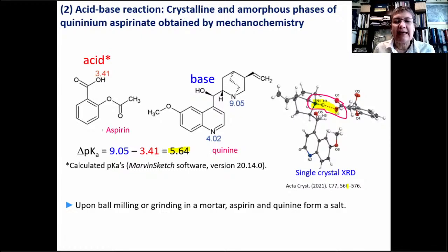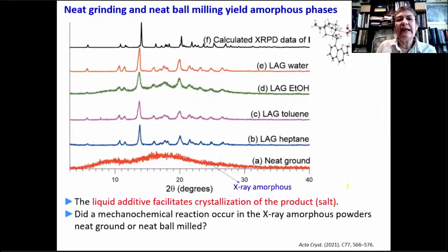In this case, various liquid additives were used: heptane, toluene, ethanol, and water. They seem to support the crystallization of this material, so a crystalline salt is obtained. In all cases, the same crystal structure is shown in the powder diffraction patterns. But using no additive, we obtain an amorphous mixture by powder diffraction.